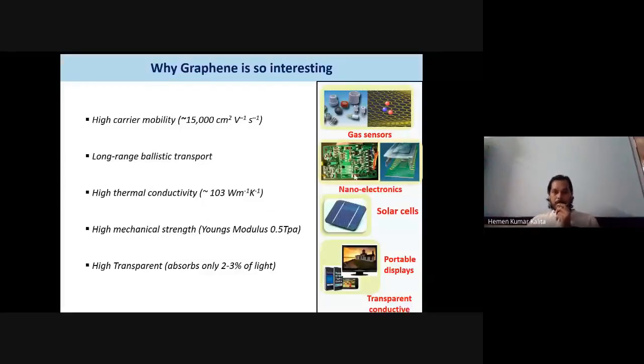So why is graphene so interesting? Andre Geim and Konstantin have got the Nobel Prize not because of discovering graphene, but because graphene has so many exciting properties. I've listed a few of them. If you can see in this slide, it has a high carrier mobility, more than silicon. It has a long range ballistic transport. That means if the carrier moves from one edge to another in graphene, there is no scattering. The scattering is very less in graphene. It's a highly thermally conductive material as well, and the mechanical strength is also very high. In fact, it is 300 times stronger than steel, and it is highly transparent as well.